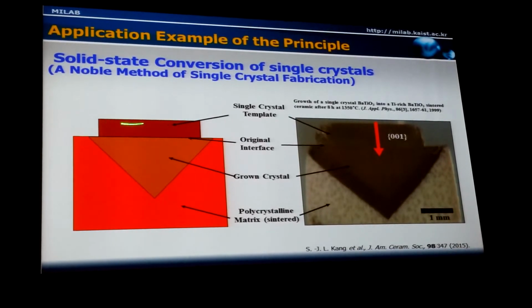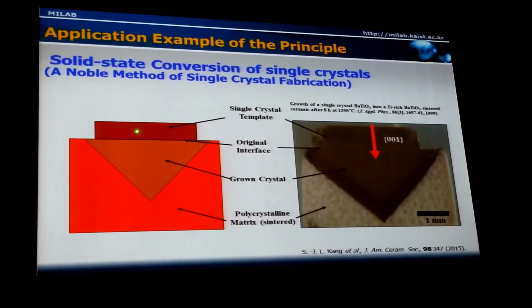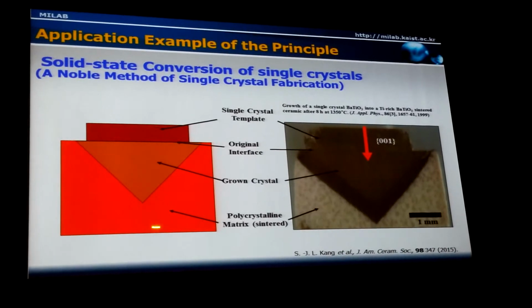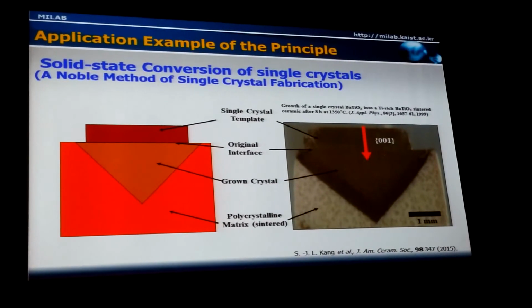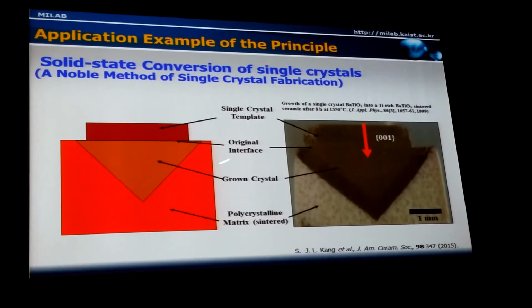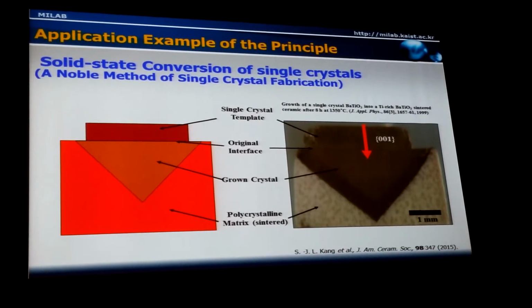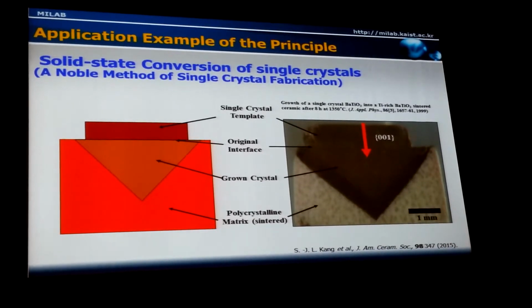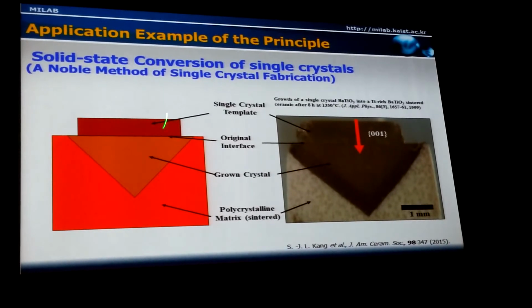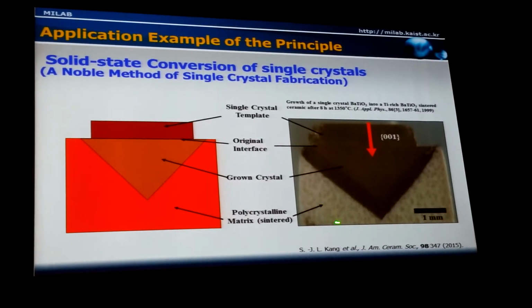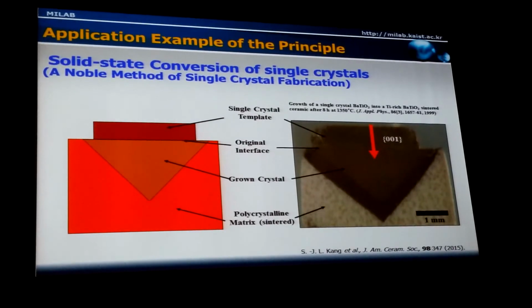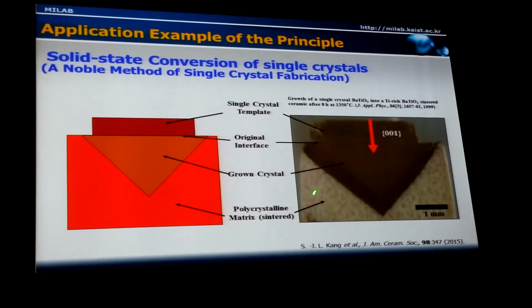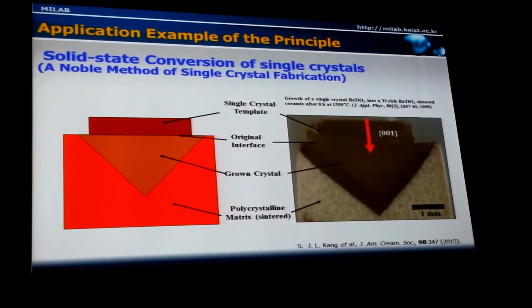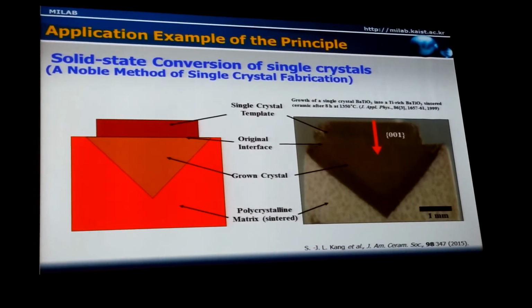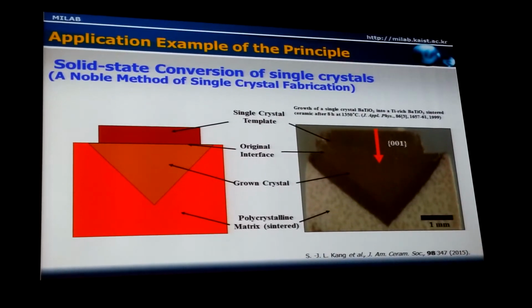And when you put a seed crystal on a polycrystal, and the seed crystal grows into the polycrystal and scavenges all the polycrystalline grains, then the polycrystal converts into a single crystal. In order to use this technique, we need to suppress the grain growth in the polycrystal. If grain growth occurs, then the large grains in the polycrystal will impede the growth of the single crystal. So we need to control the microstructure, that means suppress the grain growth in the polycrystal.